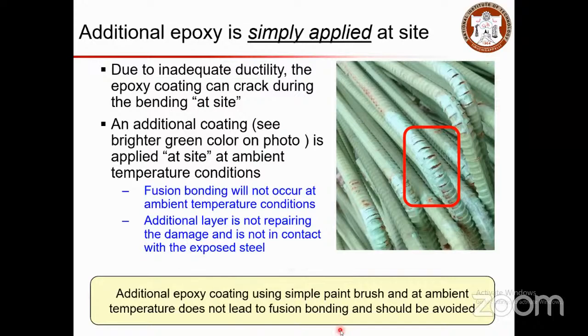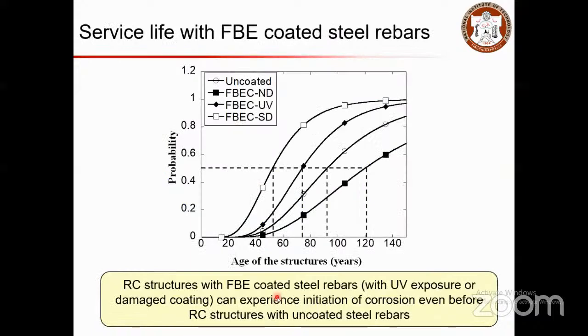So additional epoxy coating using a simple paintbrush at ambient temperature does not lead to fusion bonding, and it should be avoided. So there is a study which looks at the service life of this fusion bonded epoxy coated steel rebar. You can see this is the uncoated rebar, and this is the coated rebar without damage. And again, when you have these coated rebars exposed to atmospheric conditions, lying at the site for a long duration, there will be a degradation due to ultraviolet rays, and a degradation due to direct sun exposure as well. So this indicates no damage, this indicates ultraviolet damage, and this SD condition indicates the surface damage of your rebars.